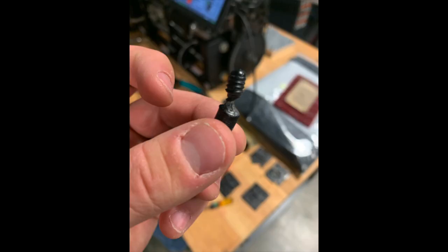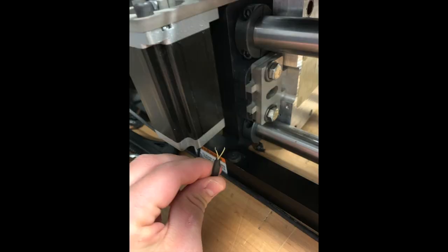At one point, there was so much flash that some molten plastic seeped into one of the vacant screw holes in the mold. We later found out that the sensor used to monitor the mold temperature was completely broken off. We think that the importance of this sensor was to regulate the temperature of the mold. This led us to the conclusion that the mold was getting too hot and causing the increase in flash.